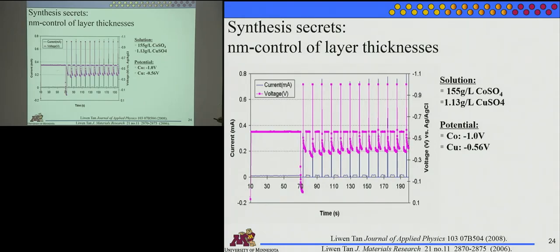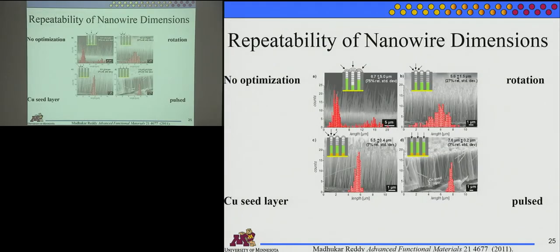Then you come down below the reduction potential of both to kind of flush out the pore and pull back in solution, and you deposit just the copper. Now you have to sit here longer because you have less of it in the solution, and you have to overcome that diffusion limitation, which was why we had the flat line on the previous curve. The point is you really have to learn your bath and then design out how you want to grow these, and then you can get very uniform layers,